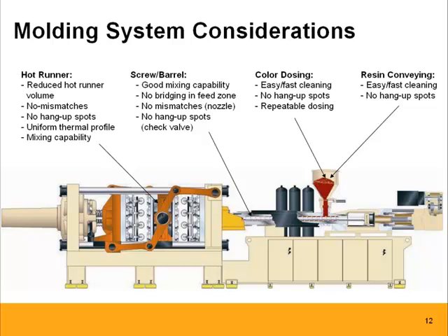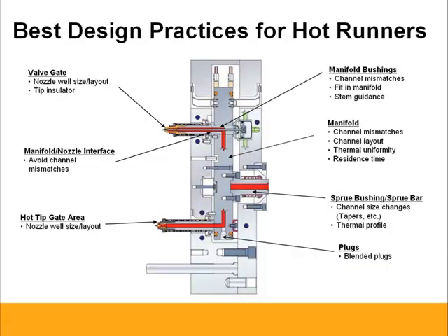So what are some of the best design practices for hot runners, or things to look out for or ask your hot runner supplier when it comes to color change? For example, in manifold bushings, make sure they have nice, round, smooth corners, and that there's no gap between the bushing or the plug and the manifold, because material can creep into these gaps. So fit is very important. Fit of the stem, very important. In the manifold itself, any kind of manifold channel mismatches should be avoided.